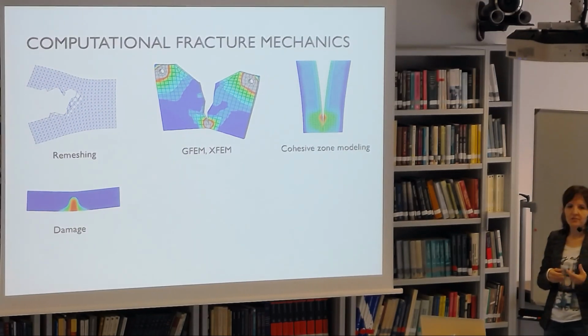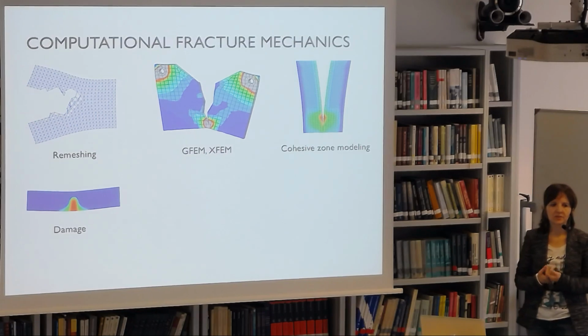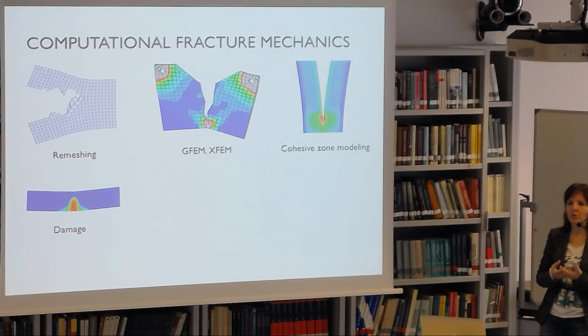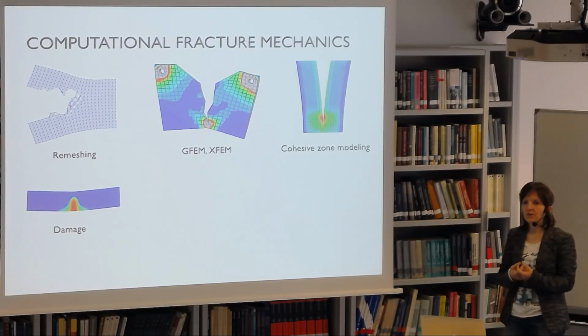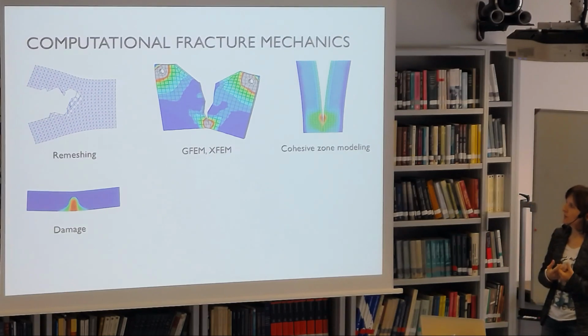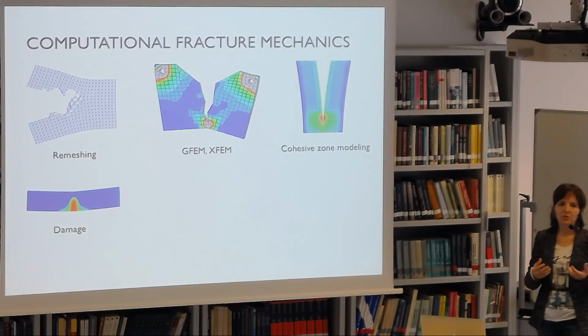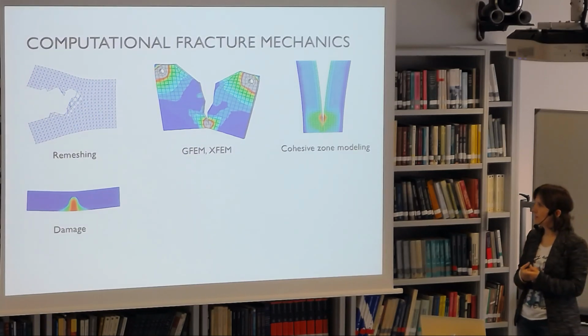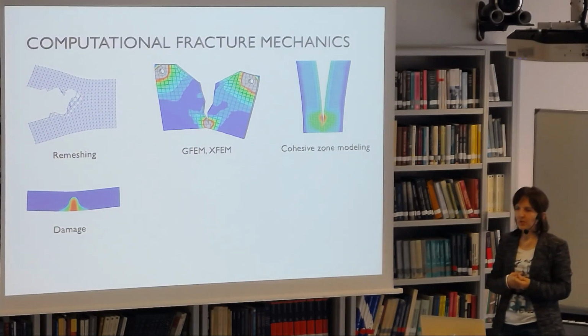Cohesive zone modeling is also very popular. It's certainly a very good choice if you know in advance where the crack is going. For instance, if you have bimaterial interfaces and know that the crack is propagating at that interface. But there are issues if you don't know. Many times you don't know upfront where the crack is going. In this case, it might be difficult to apply this approach.